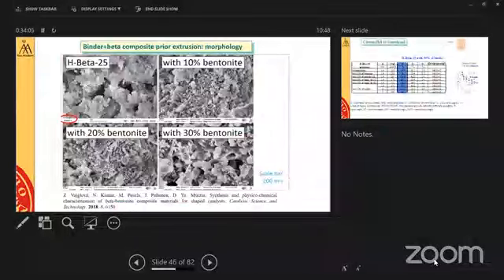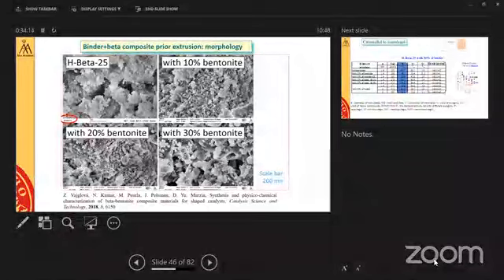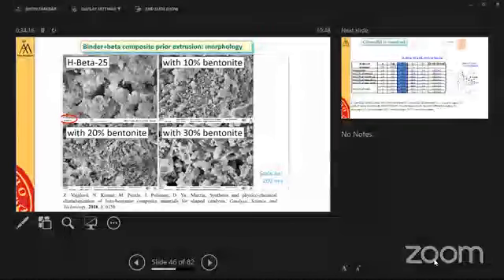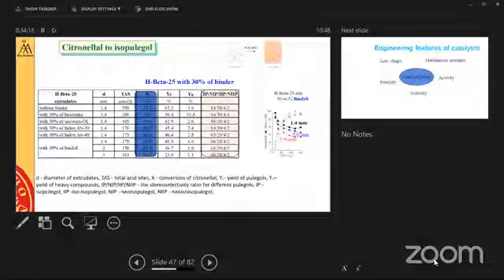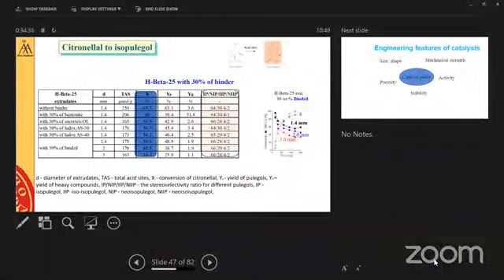Once again, it's just mechanical mixing. So morphology is changing when we add different amounts of bentonite. So we saw really differences. This is just one example. Now a few words about a very simple reaction. The one in the middle, where we have cyclization, where we need only the acid sites. Now we move to these compositions with the binders.